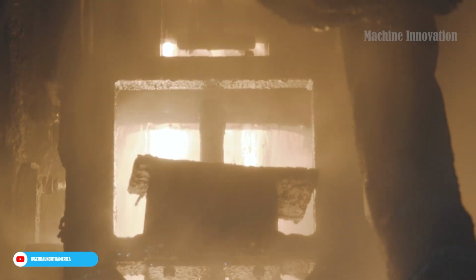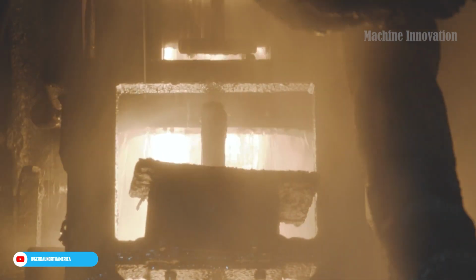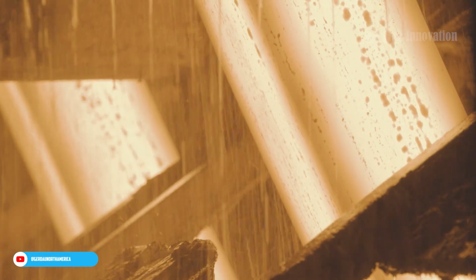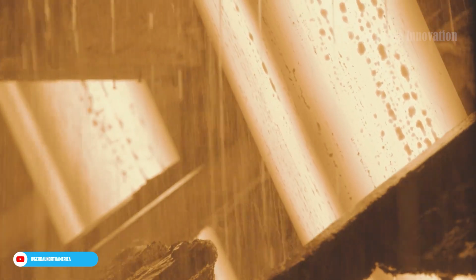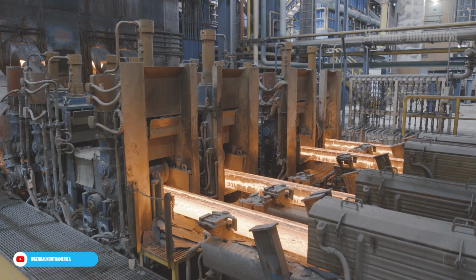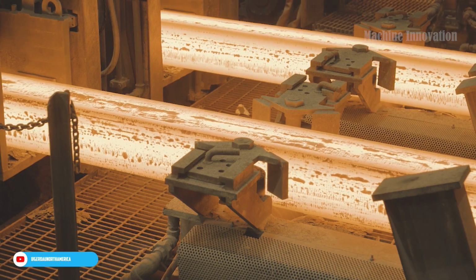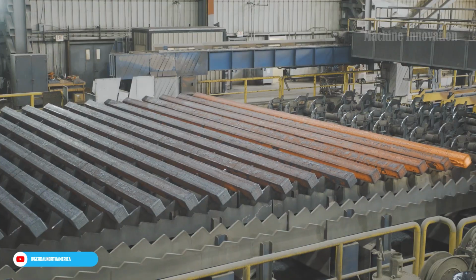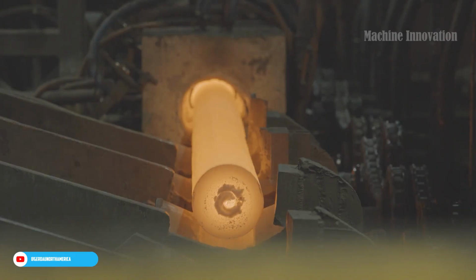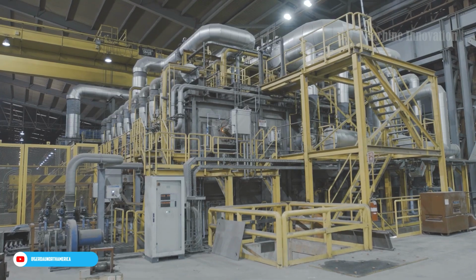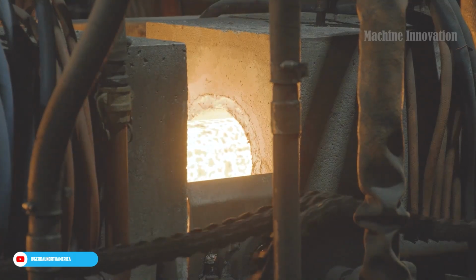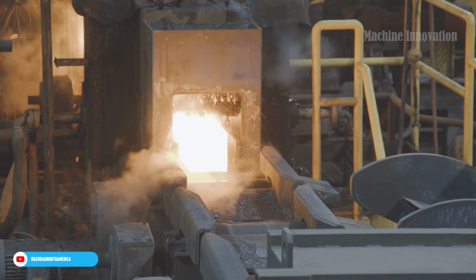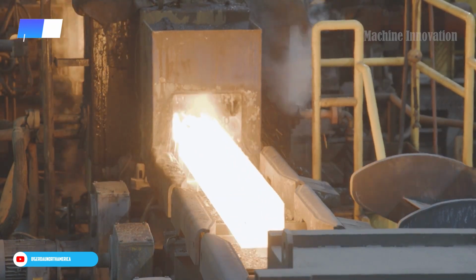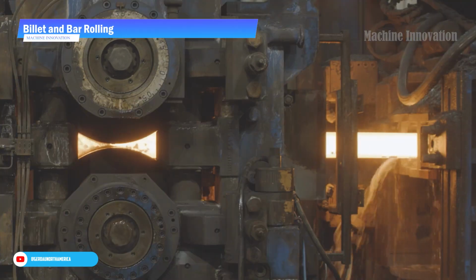This rotation helps create billets and blooms with even properties throughout the steel, ensuring that each section is consistent in strength and durability. The molten steel flows through a ceramic shroud and enters a tundish protected by argon gas. Electromagnetic stirring creates uniform heat distribution, which, combined with controlled water spray zones, cools the steel in a way that produces billets with uniform properties. Gamma radiation detectors continuously monitor mold levels, and automatic adjustments ensure high-quality outcomes.